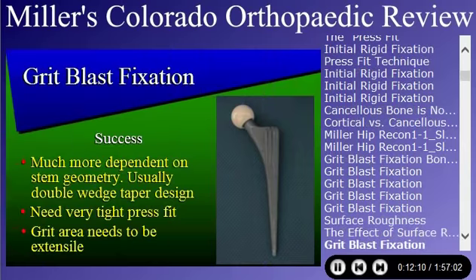The success, though, is much more dependent on stem geometry. Since you don't have a good porous coating, you really got to wedge these bad boys in there, and you got to wedge them tight. And generally what you see are these sharp tapered stems wedged right in there. They have to be a very, very tight press fit. The grit area needs to be pretty much extensile because you don't have the same strength as you do with a 3 or 4 layer porous coating. So the grit-blasted stems tend to be extensively coated all the way to the tip.